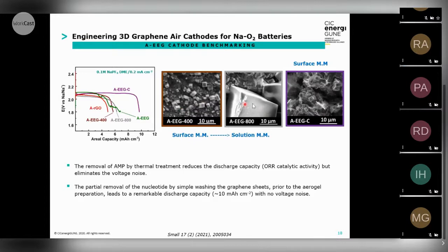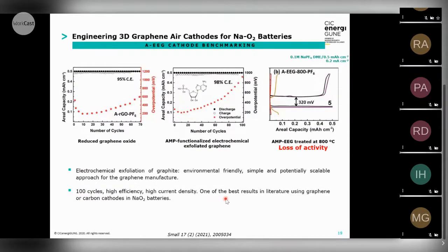Here you have the samples treated at 400 and 800 degrees, compared to the clean sample. So this means that we can have different mechanisms, from more of a surface mechanism, where you reduce the oxygen on the surface and then grow the discharge product, to more of a solution mechanism, where you have all this sodium superoxide in solution, and once it reaches a supersaturation point, these cubes precipitate. So like this, we saw that the clean sample outperforms the other samples, because maybe the quantity of AMP was too high before. And also we wanted to check the cyclability.